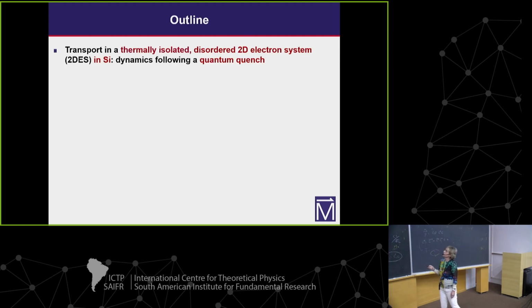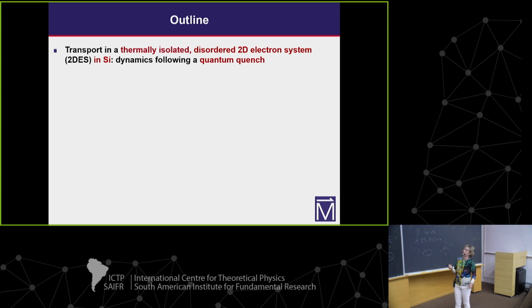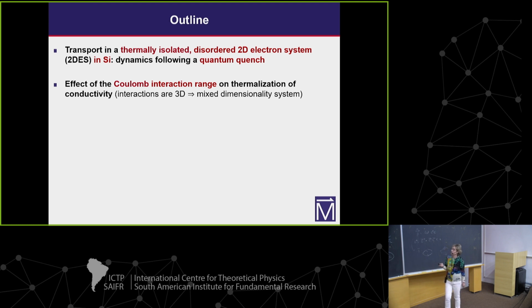So what I'm going to show you today are the results of our experiment, done on a nearly thermally isolated, strongly disordered 2D electron system. We studied the dynamics of the system following a quantum quench — a protocol in which you change one of the parameters of the system quickly and then study the time evolution, similar to what Carol was talking about yesterday. We focused on the effect of the range of the Coulomb interaction on the dynamics of the system, on thermalization. In particular, we measure conductivity.